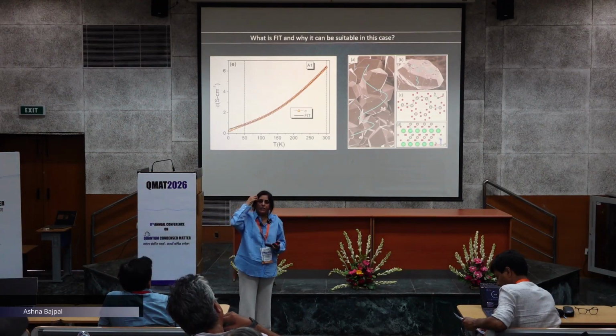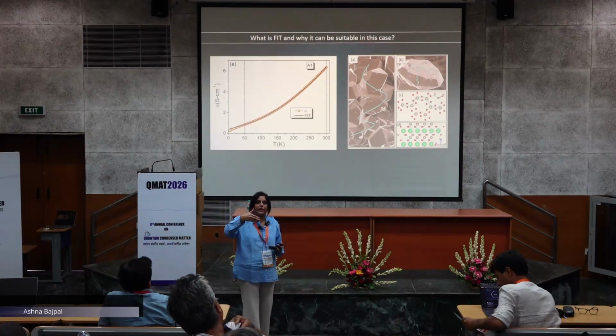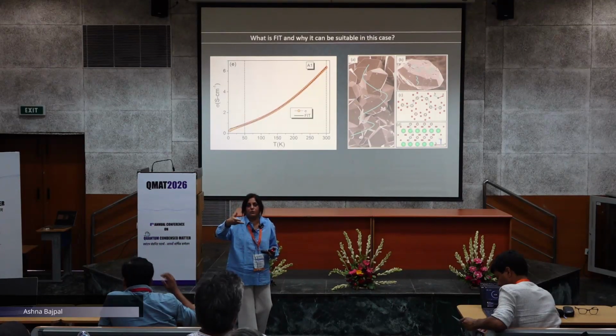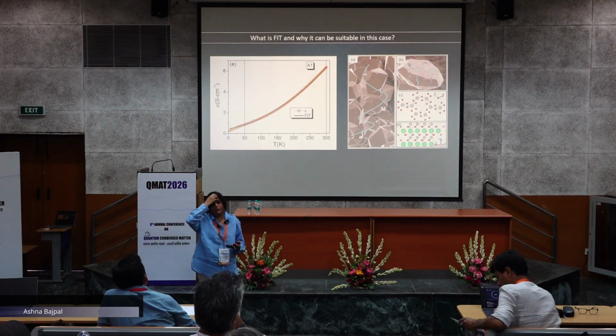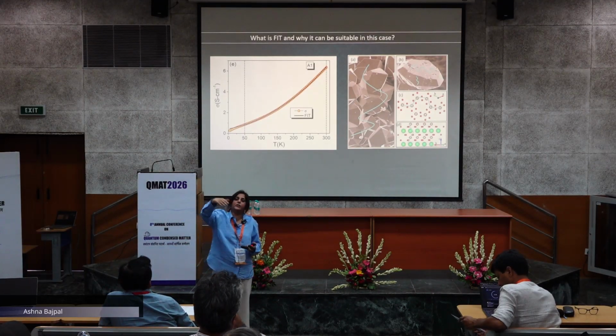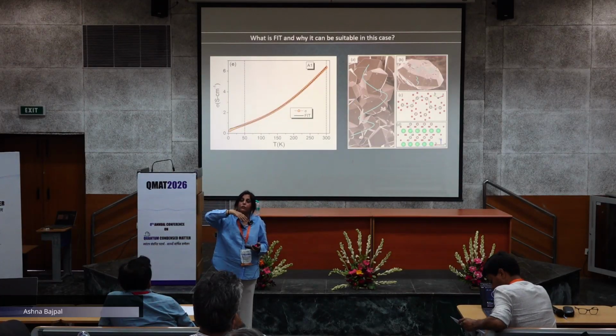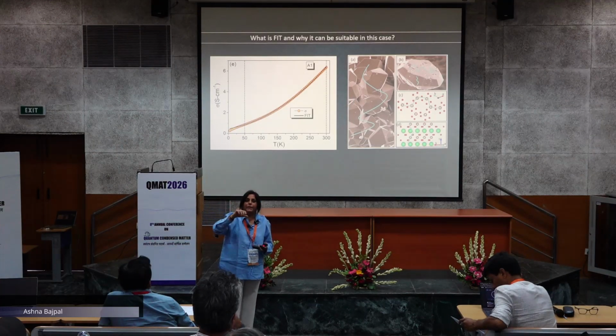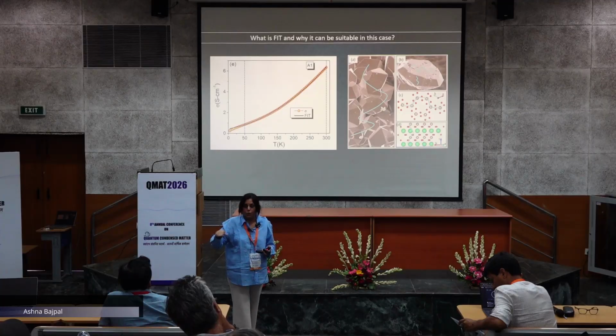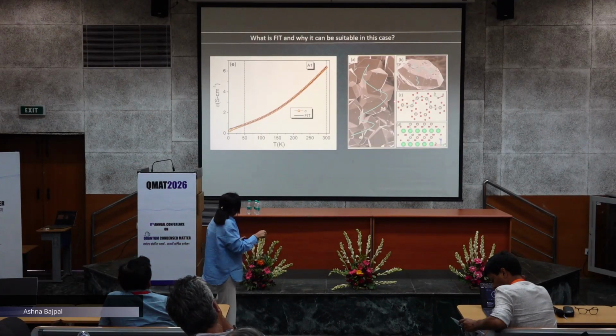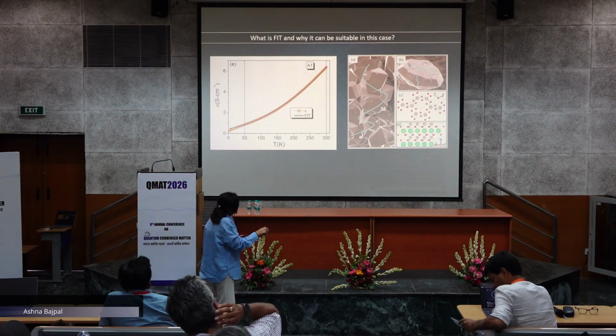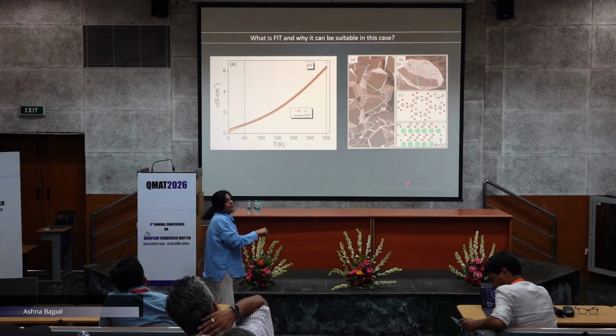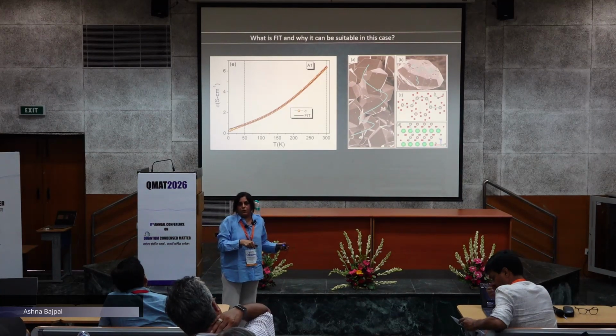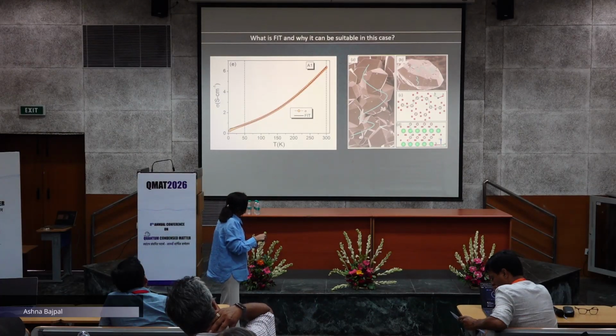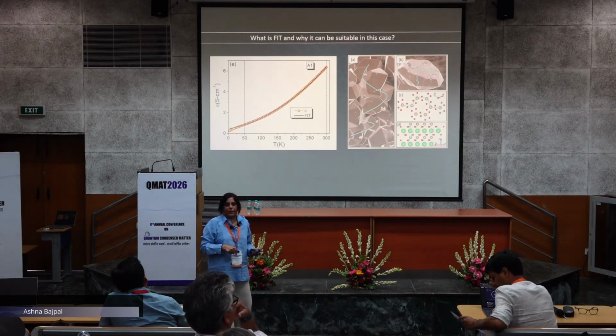So DFT calculations suggest that near the Fermi level it is Ru and O levels, and Sr levels are 1.5 electron volts away from the Fermi level. So basically the players are Ru and O, and these RuO planes are separated by insulating Sr layers, so as to say. So then, can tunneling happen through these Sr layers?